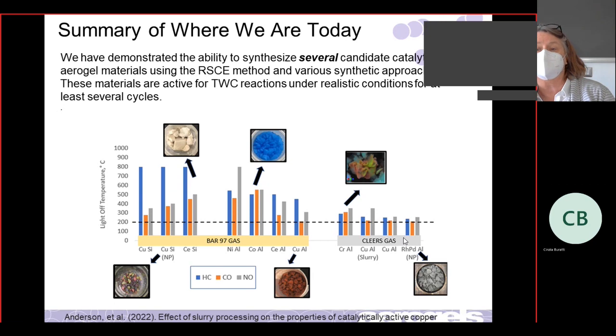And so here's a chromium alumina aerogel, not too bad. Here's our copper alumina slurry. Here's our copper alumina regular. I believe these are all dry tested. We also did some testing in humid environment, and there are some changes.